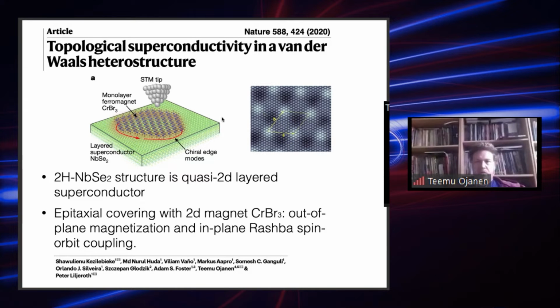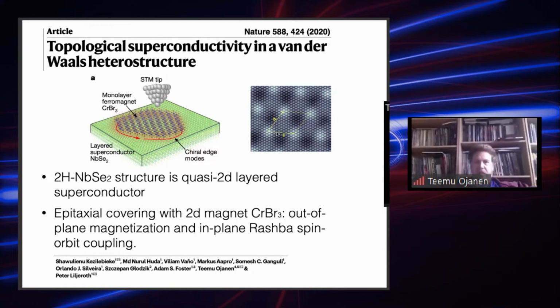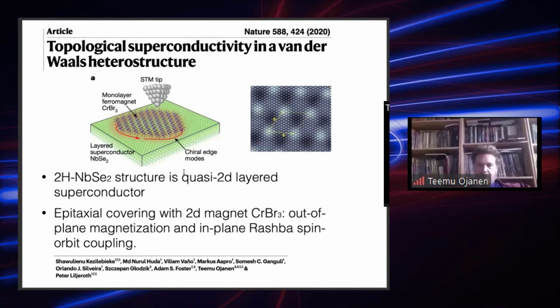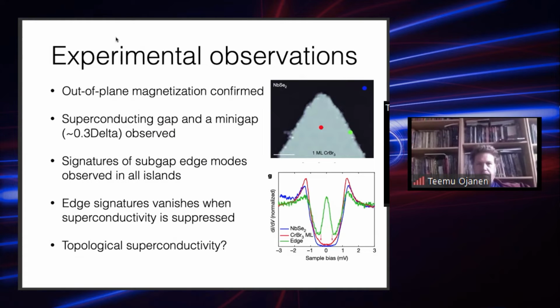And here you can see that due to the lattice mismatch of the chromium tribromide and niobium diselenide, there is a certain moire pattern somehow forming on top of the area where the monolayer ferromagnet is covering the niobium diselenide. Right. So here's a kind of a summary of experimental observations. So experimentally they observe out-of-plane magnetization. So this is an experimental fact, and that magnetization is observed in places where you have this covering by chromium tribromide.